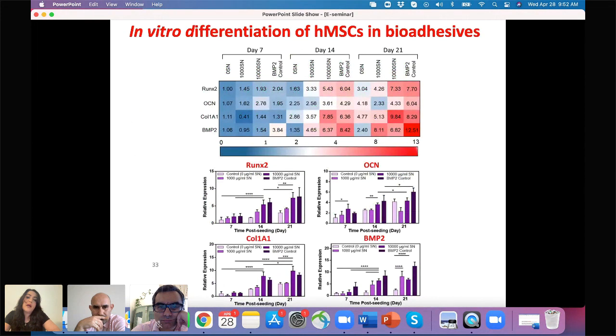We also looked into the differentiation of MSCs once we cultured them on these hydrogels. We looked into the expression of different bone-forming markers for the different groups: control, different concentrations of nanoparticles, and another control, which was BMP2 added to the culture media. With our experiment, we show that higher concentration of nanoparticles resulted in higher expression of these genes, and it was very close to the control that was the addition of BMP2 in the media. So our optimized formulation was the hydrogel that has a higher concentration of nanoparticles.